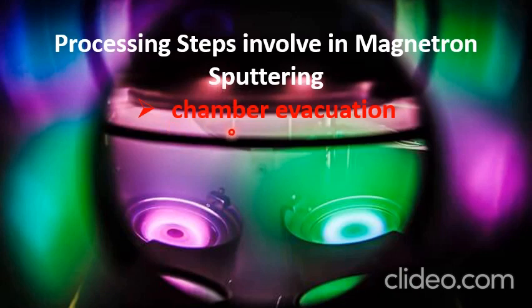So a pressure somewhere in the range of 2 × 10⁻⁶ torr is achieved in the magnetron sputtering reaction chamber. This pressure is achieved by using a combination of different types of pumps, such as rotary or turbomolecular pumps. So in the first processing step, the reaction chamber is evacuated in the range of 10⁻⁶ torr by using a combination of different types of pumps, such as turbo or rotary pumps.